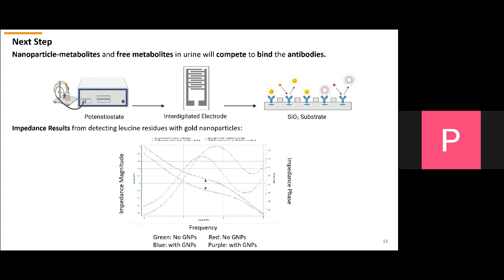Then when we add a urine sample to the electrode, any free metabolites present will unbind our nanoparticles. This is because the free metabolites have a higher affinity for the antibodies than nanoparticles do. This will cause a change in impedance, which we can then measure and determine the concentration of these free metabolites in a urine sample. And example results are shown below, where gold nanoparticles were used to detect leucine residues.